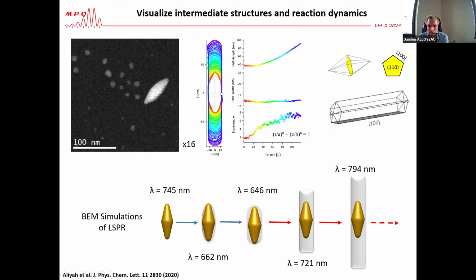The nucleation sites of the nanoparticles at the beginning are the common base of the bipyramidal seeds, which has 100 edges. And in fact, you have the transformation of those edges into 100 facets to grow those nanocubes. And you see that the length of your nano object is not increasing at the beginning. You just change the shape of your nano object.